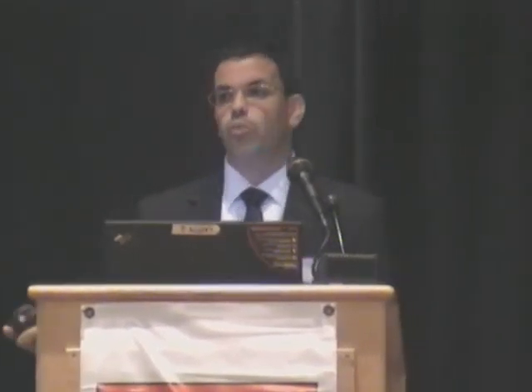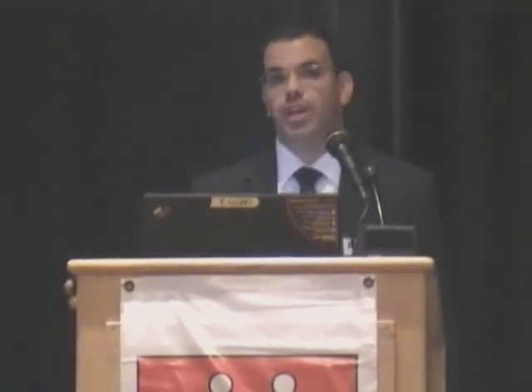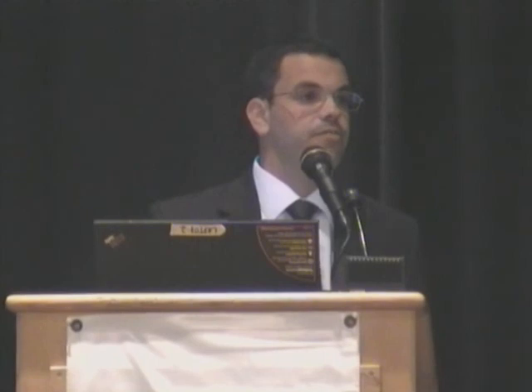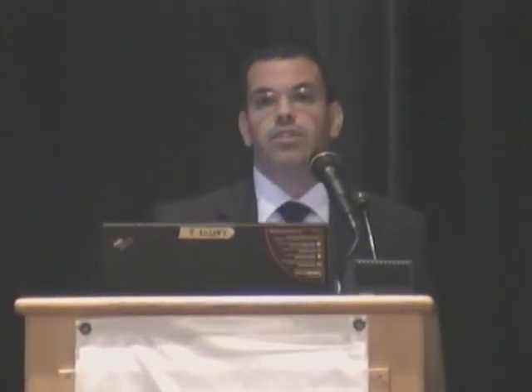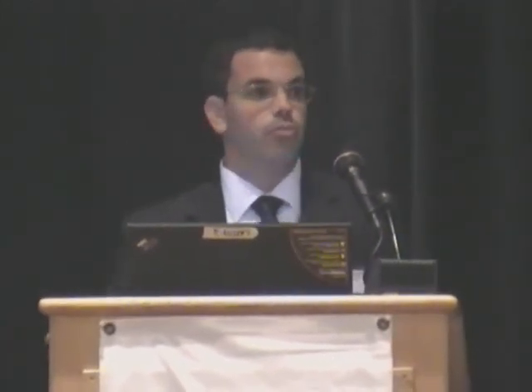And we will know, and we will be able to monitor this structure and solidification behavior day after day. Melt control. We installed a portable metallurgical inspection unit combined with a thermal analysis unit that can be applied in the foundry and can give us a good, quick reading on the modification level that we have per melt per day. Instead of going and checking the casting itself, we were starting to check the furnaces themselves.